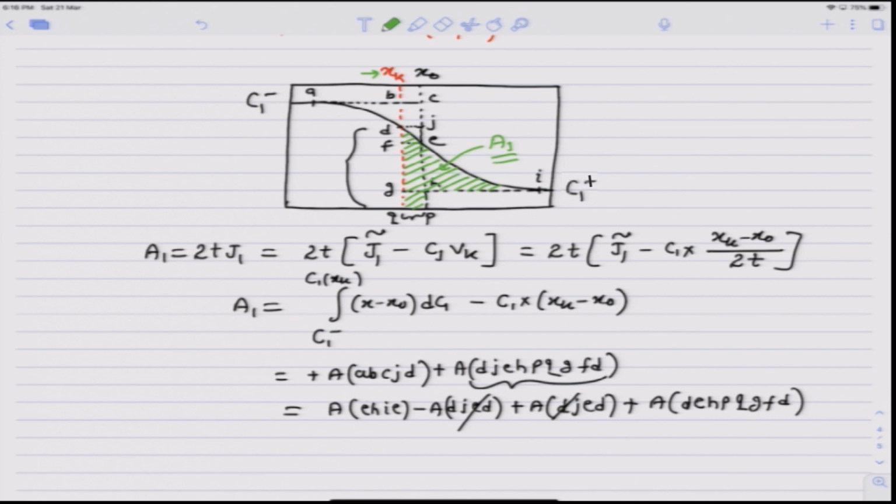Now if I want to evaluate ternary intrinsic diffusion coefficients, it is much more difficult because we will need at least two diffusion couples yielding the marker location at the same composition, which is almost not possible to obtain. But we do need the relations between intrinsic and interdiffusion coefficients in order to relate these phenomenological coefficients to the fundamental mobilities and jump frequencies. So let us quickly look into it.